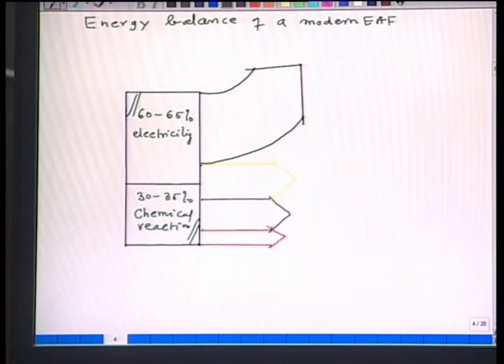On the right hand side, around 53% of energy is carried by steel, because you are tapping the steel at around 1600 or plus 1650. So, it will also carry a very large amount of heat. So, you are seeing 53% of the total energy input into the electric arc furnace is being carried away by the steel. Of course, you cannot do much.